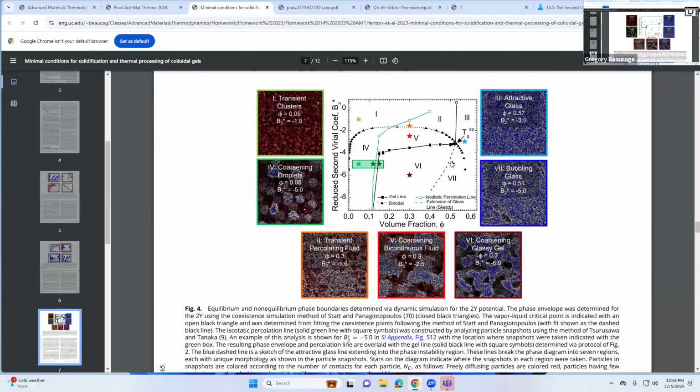So obviously, or maybe obviously, at high concentration you get the glassy state because things get stuck at high concentration. So the glassy would be the high end, 3 and 7. And then in between, you have this flat line, the gelation curve. It occurs at the same temperature for all different concentrations. It doesn't matter. And then he gets to gels that fall apart. They first form and then destroy themselves because gravity rips them apart, because they're at such low concentration. They gel, but they fall apart. So that's regimes 1 and 4. 1 would be in the single phase, 4 is in the two phase.